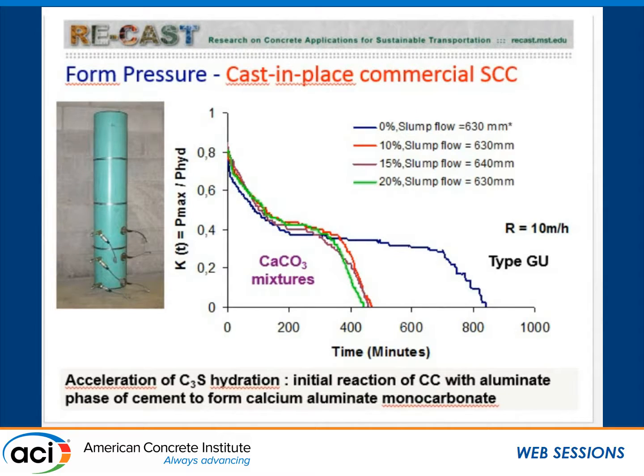And what we think is happening is that you get an acceleration of the hydration of C3S. Eric mentioned that you get nucleation, pumping of the silicate because of the high calcium. But also you get an initial reaction between the calcium carbonate and the aluminum phase, the C3A especially, to form some calcium aluminate monocarbonate. And this is something that has been documented in the literature that can explain some of the early strength development when you are using calcium carbonate, especially finely ground calcium carbonate. So this is an interesting surprise. You came across it by accident, but you can definitely take advantage of this property.